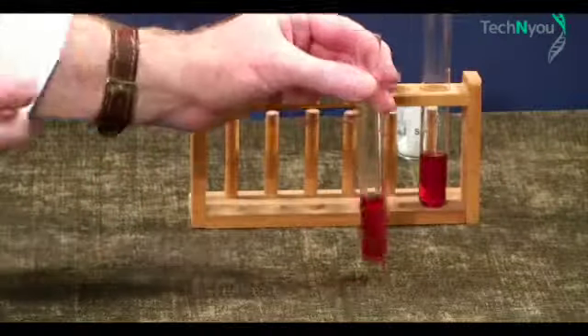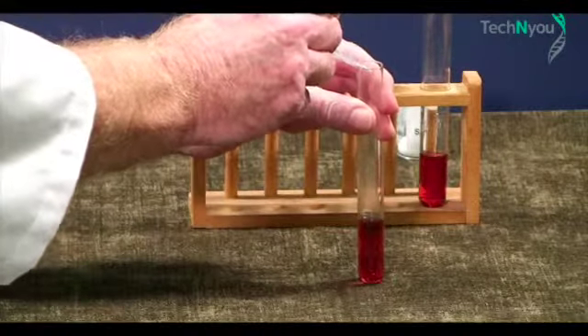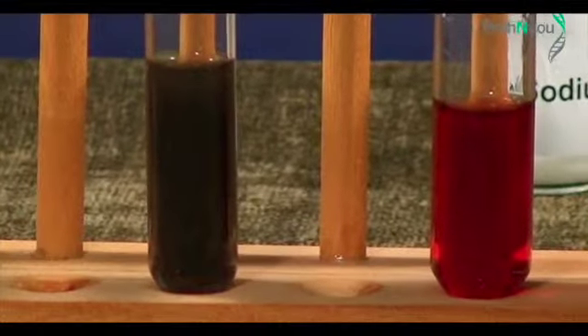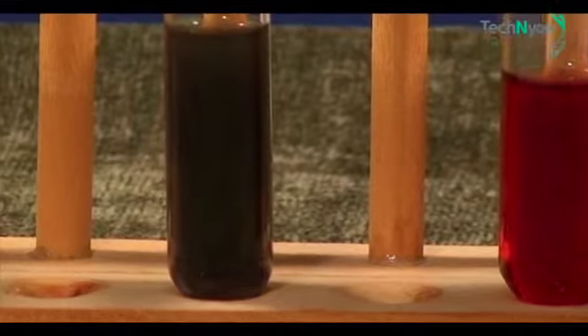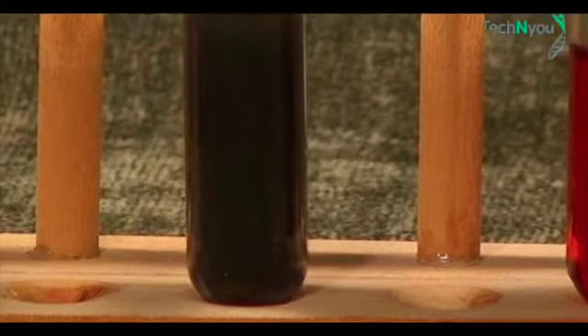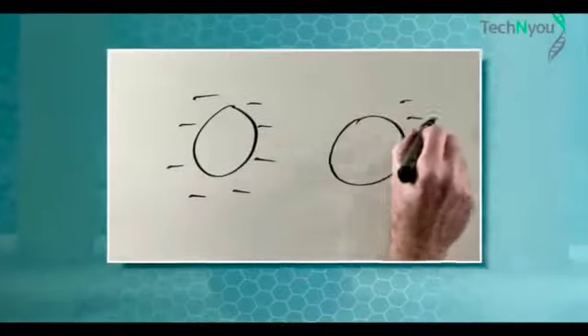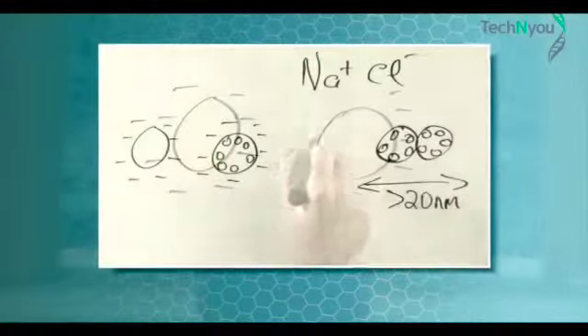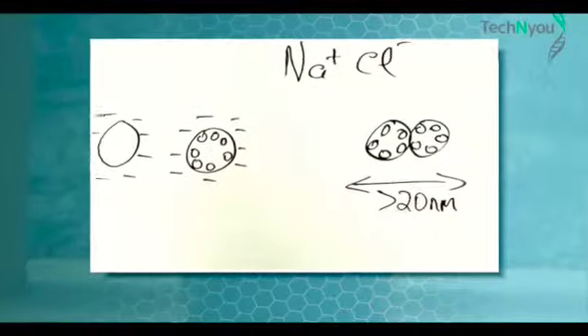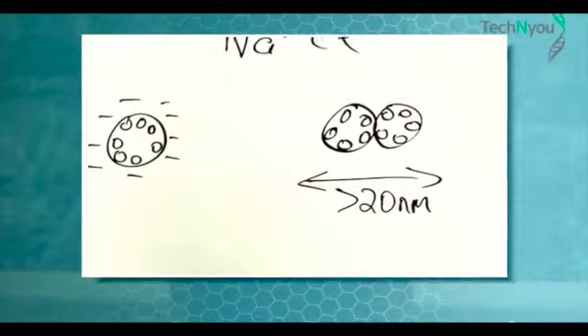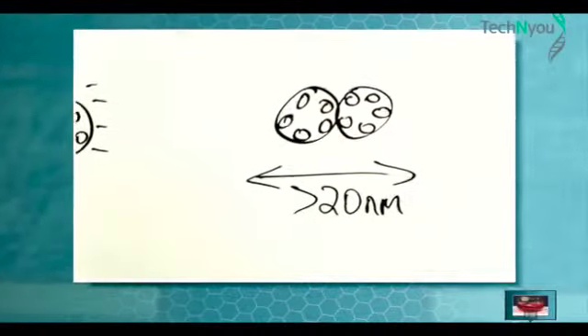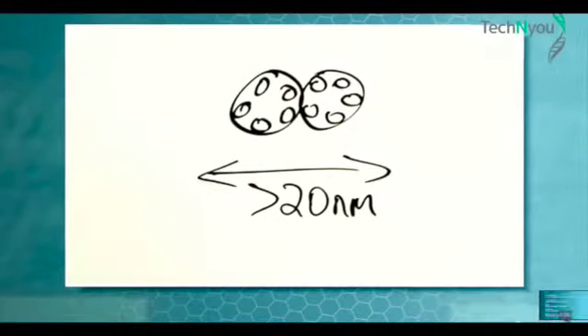We will add to one of the test tubes a few drops of sodium chloride solution and shake it well. We observe darkening of the color. By adding sodium chloride solution to the original gold nanoparticles, we have caused the particles to increase in size, which affects the way they reflect light and therefore changes the observed color. Adding sodium chloride disturbs the electrostatic sheath around each gold nanoparticle, resulting in positive attraction, agglomeration, and therefore size change.